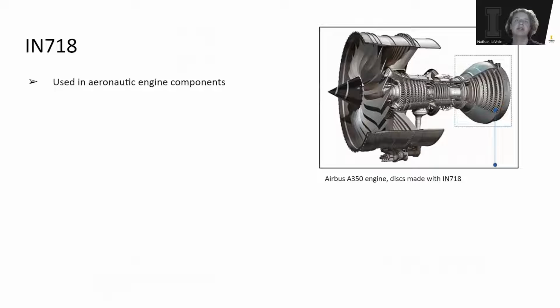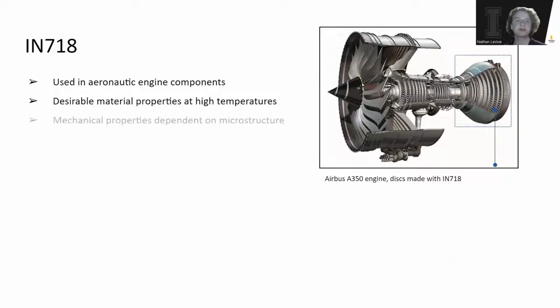Inconel 718 is a polycrystalline superalloy used primarily in aeronautic engine components. This precipitation hardening nickel chromium alloy is desirable for aerospace applications because it is characterized by good tensile, fatigue, creep, and rupture strength at temperatures up to 750 degrees Celsius. However, Inconel 718's mechanical properties vary greatly depending on its underlying microstructure, including grain size, orientation, manufacturing technique, and secondary composites, which make Inconel 718 hard to predict. When dealing with such variable substances, a method must be derived for deriving mechanical properties.